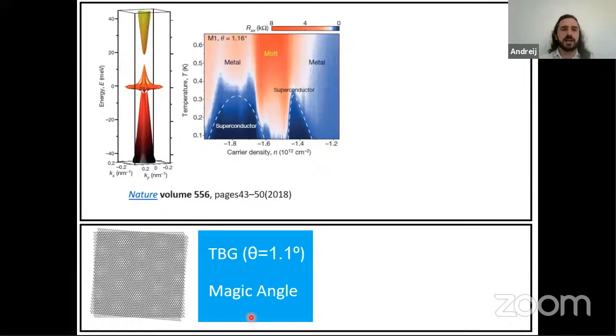So the researchers, Yuan Cao and Pablo Jarillo-Herrero from MIT, figured out that in this regime, the electronic structure abruptly changes. So I draw your attention here to the flat band, which is located here. And they also measured the resistance of TBG devices as a function of the temperature and carrier density, and they observed superconductivity and Mott insulator domes.